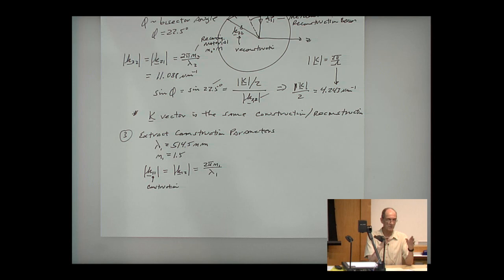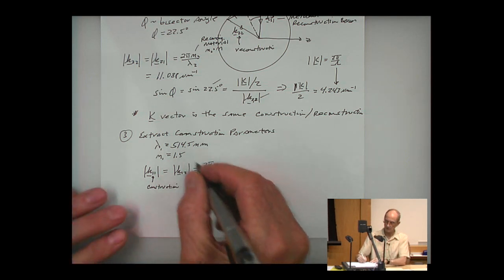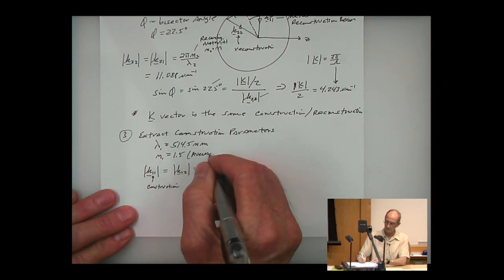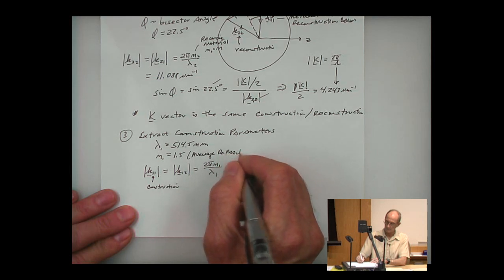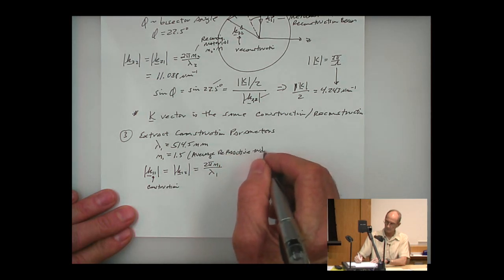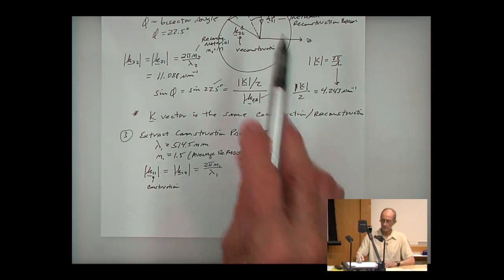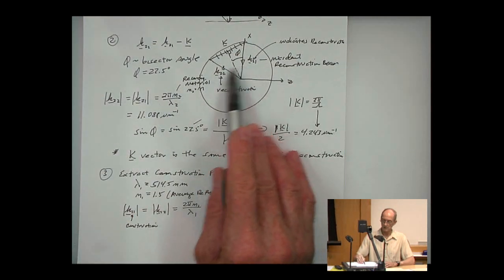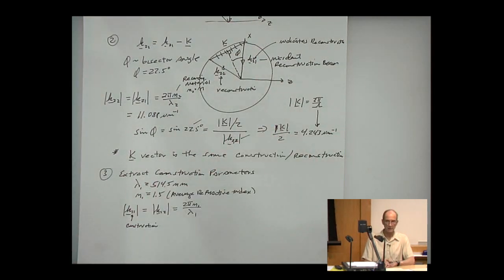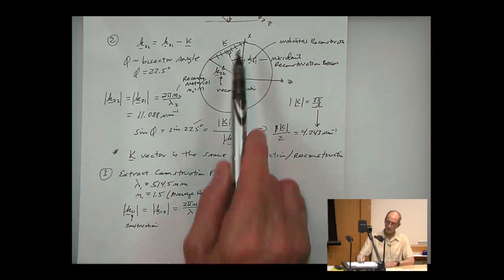Now, it's possible, and most of the time it happens, that this refractive index actually is different for the material during the construction and after you process it. It's especially true for wet process materials like silver halide film and dichromated gelatin films. They will change their average refractive index. And so, again, that will change slightly the orientation of those propagation vectors with respect to that grating vector.